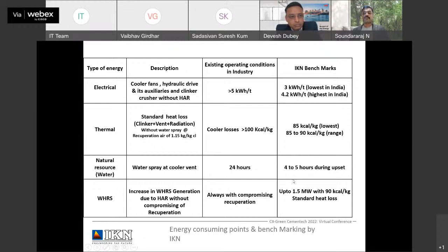So WHRS, if you see the benchmarking number for a 10,000 TPD, is increased in WHR potential by 1.5 megawatt compared to a non-recirculating cooler with sustained, standard normalized cooler losses of 90 kilocalorie. That means you have your cake and you can eat it too.